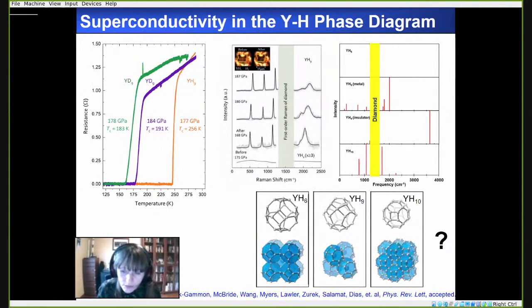So one of my collaborators, Ranga Dias at the University of Rochester, recently made a yttrium hydride phase whose Tc he was able to measure. However, because of the problem that these systems have so much hydrogen, Ranga wanted to use a novel characterization technique, Raman spectroscopy, to characterize the phases. So he was able to attain the Raman spectrum of the phase as a function of pressure, and wanted to work with us theoreticians to see if we could try to identify what the phase could be. And as I note here, the highest superconducting critical temperature that Ranga's group measured was on the order of 256 Kelvin at 180 gigapascals.